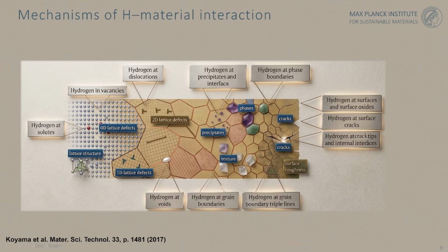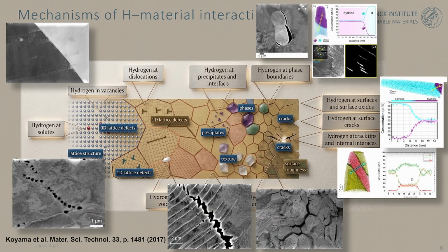And these are just a few microstructure examples from preceding papers where you see where, for instance, the hydrogen here is forming the HELP mechanism, where you have huge pileups with stress peaks and so on. Or here on this picture, you see massive porosity formation that you can see, for instance, in sour gas environments when you use nickel or stainless steels. Or here you have the interplay of localized deformation and shear band formation plus decohesion at the interfaces. Here you see classical decohesion, where the crack clearly follows the individual interfaces.